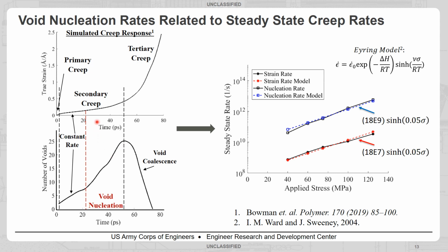So what we found was in the secondary creep regime, we had this constant creep rate, which is what we should see, but we also were able to find that you had a constant void nucleation rate in this regime. So you can plot those two together and you find that at different applied stresses, they're directly related to each other. The slopes are the same. You just have a shift on the y-axis between the strain rate and the nucleation rate. And both of these could be fit with a model, so having the strain rate, we could then predict what the nucleation rate would be.